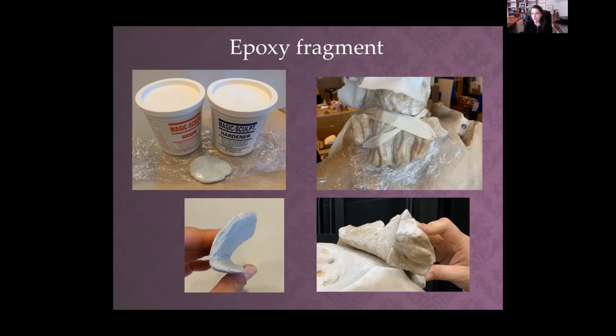And so we wanted to make it a much tighter join, and we ended up making an epoxy fragment to fit inside there. So we took epoxy putty and pushed it between 2 pieces of saran wrap, put the mullet in place. So we had a fragment that fit the void perfectly. And so when we adhered all of them together, the joints were much tighter and much more stable because the mullet was so important to structural stability of the head join onto the body.